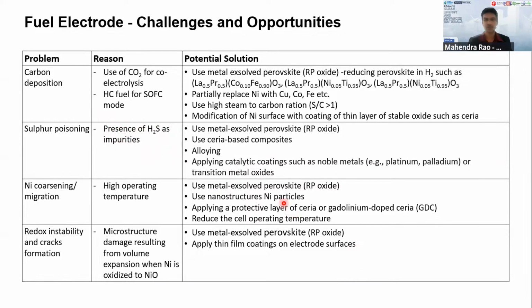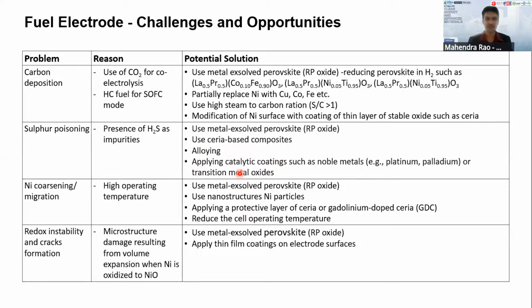Sulfur poisoning, this is typically due to the presence of hydrogen sulfide in the hydrocarbon fuel. So this is a very important issue that we need to consider, as nickel can be easily poisoned by this sulfur to form nickel sulfide, and then it will deactivate the catalyst for the efficient oxidation of fuel. So again, people prefer to use some of the solutions such as alloying, ceria-based composites, okay, applying the coating of noble materials, such as noble metals. All these challenges, we need to have some solutions. So these are some of the solutions proposed by many studies recently.